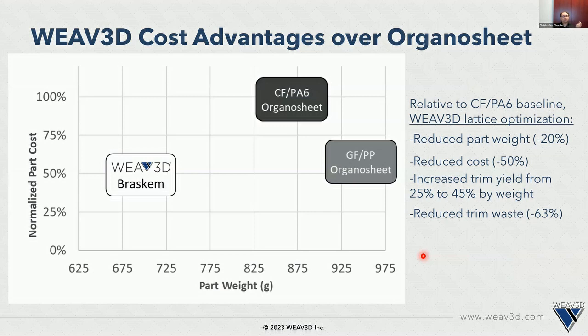So the advantage of this approach is that compared to a carbon fiber PA6 organosheet, we were 50% cheaper, actually cheaper than a glass fiber organosheet. And that glass fiber organosheet did not meet the performance requirements, whereas our solution does. And we were even 20% lighter than the carbon fiber organosheet, which is kind of shocking.